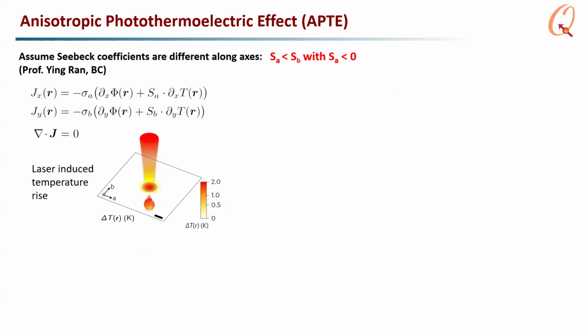So how do I understand that? We work with Professor Ying Ran at Boston College, where we can understand this due to an anisotropic photothermoelectric effect. So it's not due to any nonlinear susceptibility, it's due to laser-induced heat. But it's an interesting effect because the laser-induced temperature rise induces a gradient that drives currents due to the Seebeck effect.